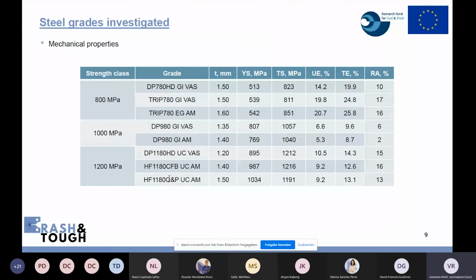And in the class 1200 megapascal, we had one DBF grade with low yield ratio, with lower yield strength, and one DBF grade with higher yield ratio, with high yield strength. Both DBF grades had the same content of retained austenite. And as I said, we had one QP grade, and this QP grade showed the highest yield ratio, the highest yield strength, and also quite high total elongations.